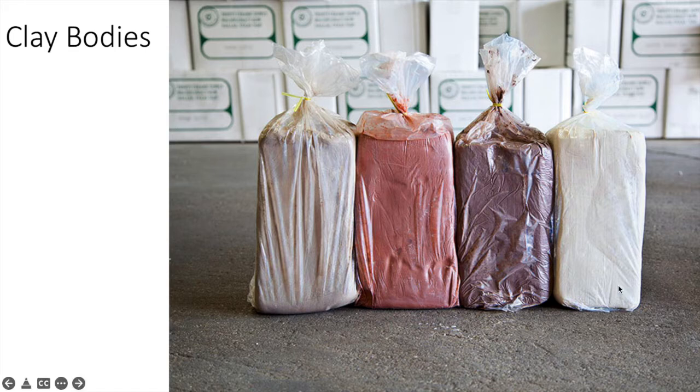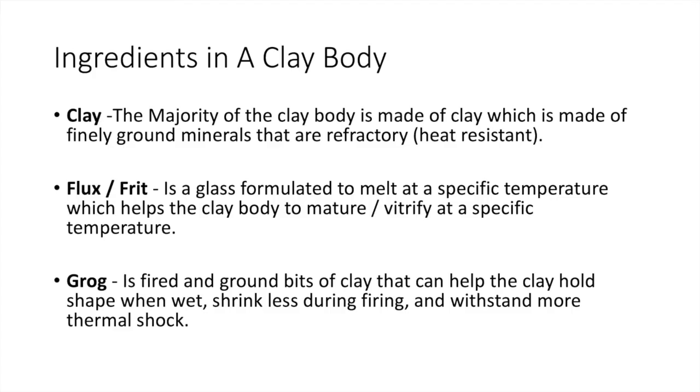And then this one is most likely a porcelain, a pure, mostly kaolin clay that's going to be a mostly primary clay, not going to have grog in it. It's going to have a beautiful white color when it's fired. Glazes are going to look real nice on it, but it's going to be a pain to deal with because it's going to feel like butter because it has no body to it.